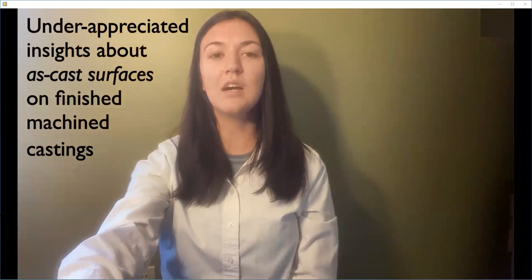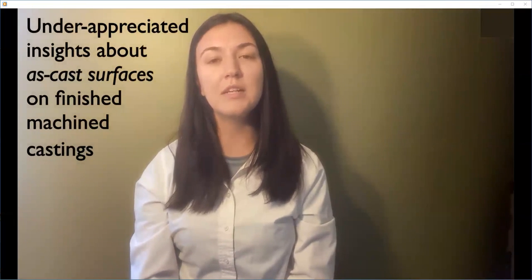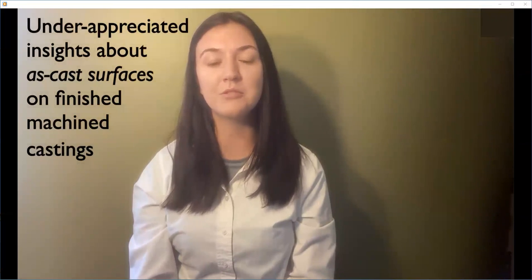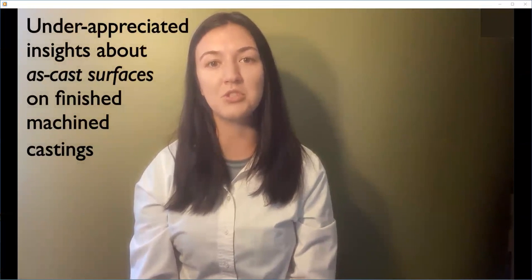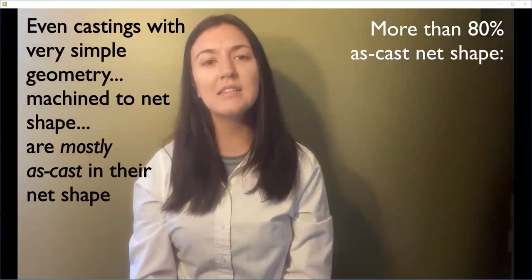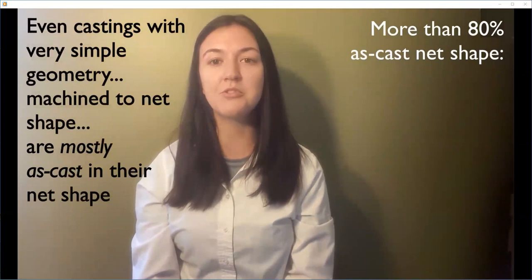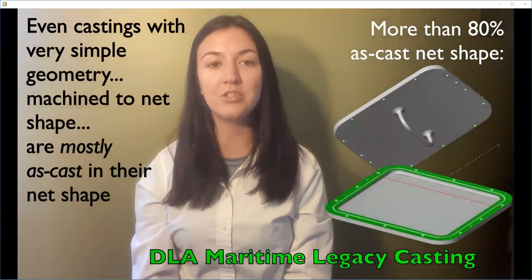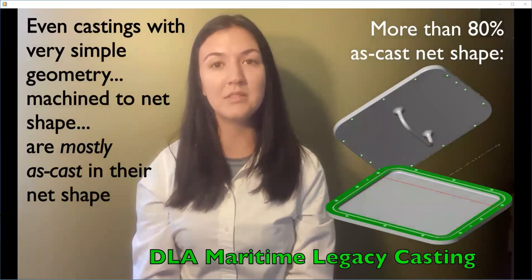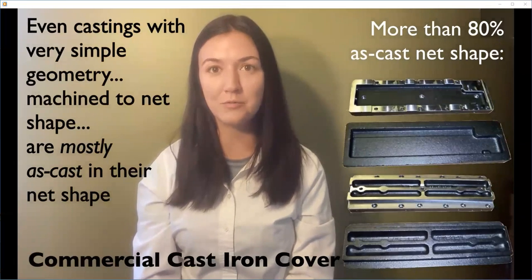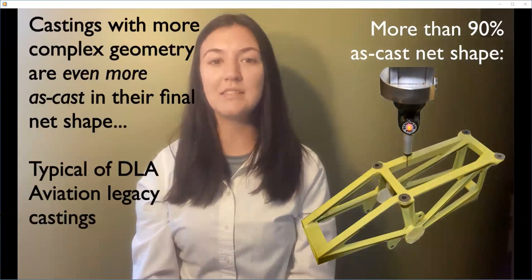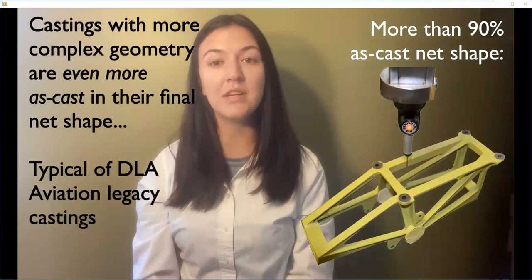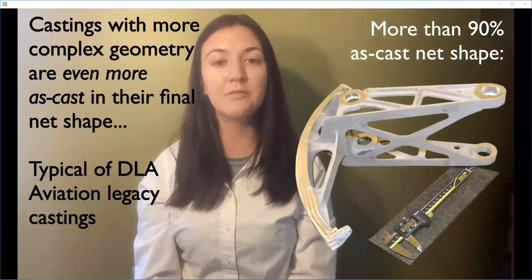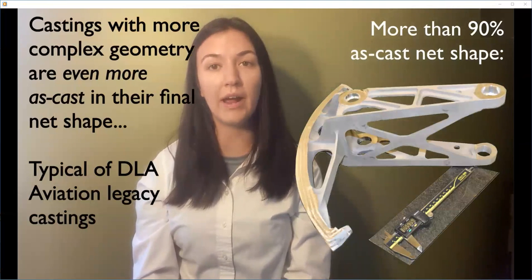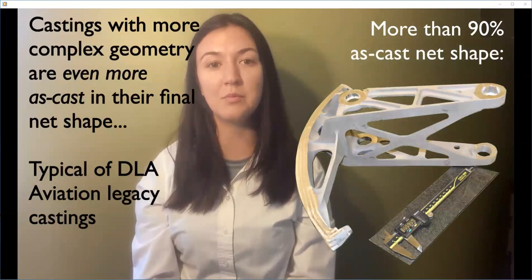The significance of as-cast surfaces can be put in perspective with these underappreciated insights about finished machined castings. Castings with very simple as-cast geometry machined to more complex net shape are still 80% or more as-cast in their final net shape. Castings with more complex as-cast geometry, as are typical DLA legacy castings, are 90%, 95%, and sometimes even more as-cast in their final net shape.